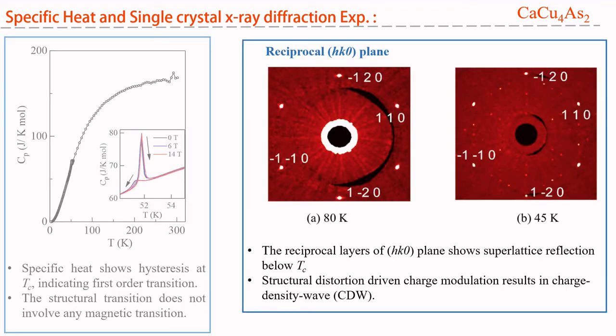The single crystal X-ray diffraction of HK0 plane is shown here. At 80 K, above the transition temperature, the bright diffraction spots correspond to primary planes. But at 45 K, below the transition temperature, it shows multiple satellite peaks, suggesting structural distortion which causes charge density wave.